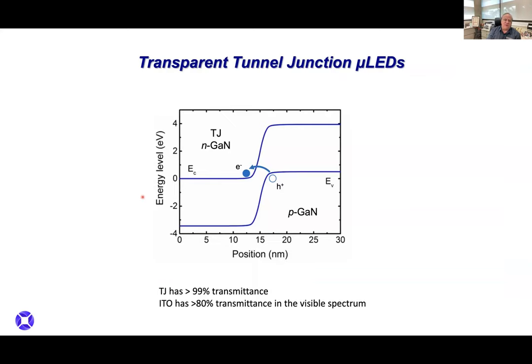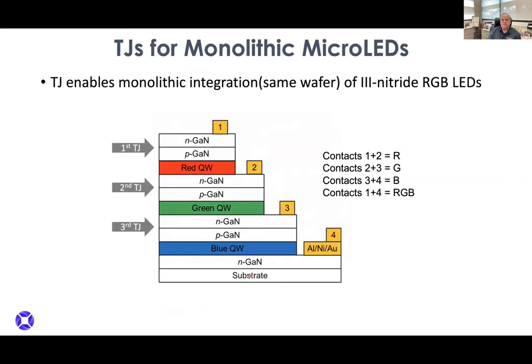The other technology we wanted to develop is what's called a tunnel junction for the top contact. What a tunnel junction is, is tunneling basically of electrons out of P-type material. And what that lets you do is replace the top P-type contact. On top of P-type, we usually put what's called indium tin oxide, or ITO. And ITO only has about 80% transmission. Tunnel junctions, being a wider band gap than blue, have 99% transmission. So this will actually help the efficiency of our micro-LEDs. And it also does something even better.